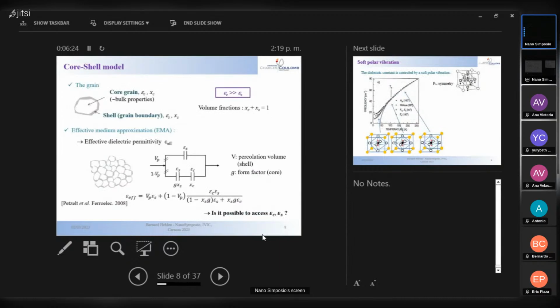So to understand this behavior, we have to go into the details of the shape of the grains in case of ferroelectric materials. In this system, you have what we call the core-shell model. Due to the growing of the grains, you have two distinct regions. You have a core here, which is made of the perfect material, and you have a shell which surrounds the core